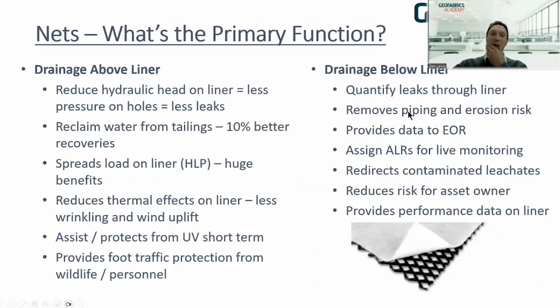What's the primary function? Well, in the mining sector, trying to relate this back to mining applications, reducing hydraulic head on liners if it is above the liner, that is, and provides less pressure over the hole, so you get less leaks, or slower flowing leaks effectively. Reclaiming water, as I said, 10% better recoveries we're hearing on other projects. It spreads the load onto the liner if it is above the liner as well, so it almost performs like a cushion. I believe we've got some data from that on the Canman 2 project from years back. So that's kind of ideal for heap leach pads where you want some drainage and some cushion protection on your membrane.